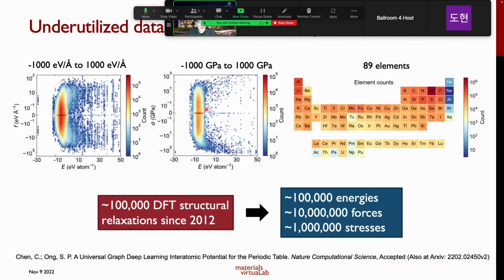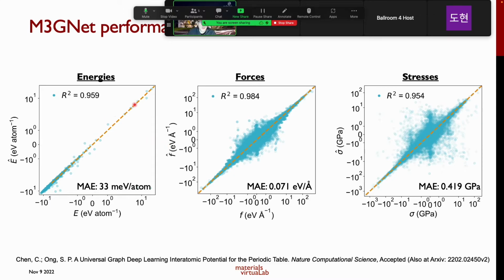Now, to do this, we basically rely on underutilized data in the Materials Project. The Materials Project has performed about 100,000 plus DFT structure relaxations since 2012. This gives us about 100,000 energies, about 10 million forces, and about 1 million stresses. And it actually also covers about 89 elements of the periodic table. Okay. So what we did was we basically took all this data and threw it into our M3GNet model and trained a universal potential that can work across all 89 elements. Okay, so these are the performance metrics.